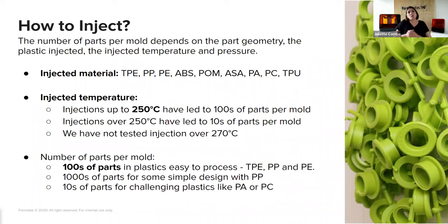And what I really want to stress is that it really depends on the geometry and the situation. So we cannot really say with a 3D printed mold you can do that many parts, or this is the result for sure that you're going to get. It will always depend on the part geometry and what you're trying to produce. But what we've observed is that injection up to 250 degrees has really good results, about hundreds of parts. So this is the mold longevity. And over 250 degrees, we've had some results, but more about tens of parts, so the mold will deteriorate much faster. And then we have not tested over 270 degrees.